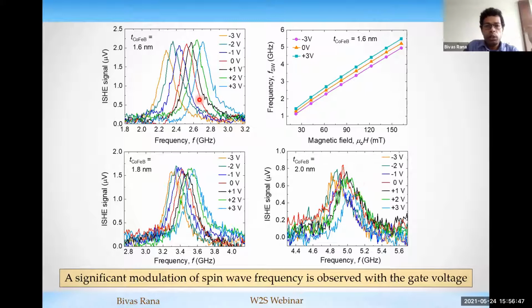You can see that for lower thickness of cobalt iron boron film, where the perpendicular anisotropy is very close to the Ms value or the demagnetizing field, the VCMA coefficient is much higher, so we can tune the frequency by, for example, 500 or 600 megahertz only by applying 6 volt in the system. Of course, we cannot change the spin wave frequency much if we increase the thickness of cobalt iron boron, because of the lower value of the voltage control magnetic anisotropy.